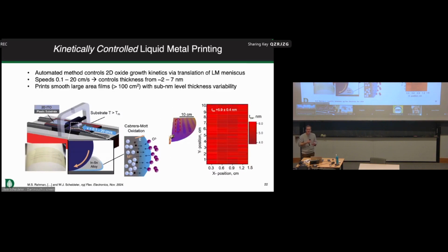We have heterostructures. The third mechanism that we've been exploring more recently is the kinetics of that process. How do we control the growth and the thickness of that 2D oxide? I said before that we could print it, but if we can print it, that means we also have control over the dynamics of this liquid metal meniscus. If we change the speed at which we deform the meniscus, what we're also doing indirectly is controlling how thick that oxide is going to grow before we transfer it to the substrate.